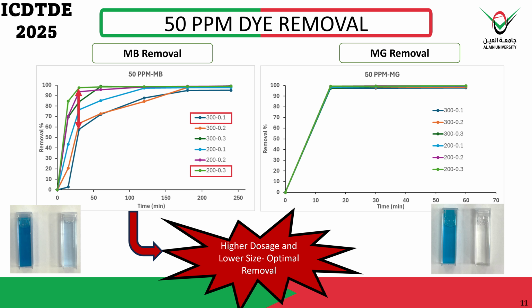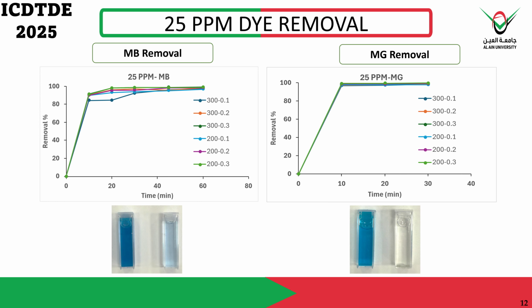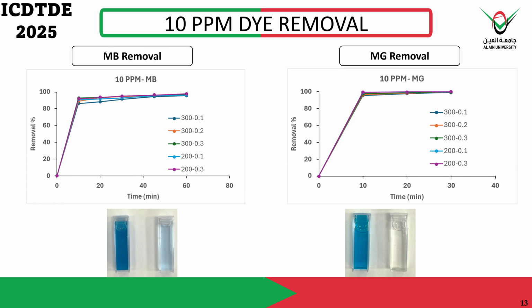And as for MG, it reached nearly 100% removal within the first 15 minutes, which tells us that our adsorbent works perfectly with MG. At 25 ppm, a similar trend was observed, confirming the effectiveness of the geopolymer adsorbent across different concentrations. At 10 ppm, near complete dye removal was achieved, indicating a strong adsorption performance at a low contaminant concentration.